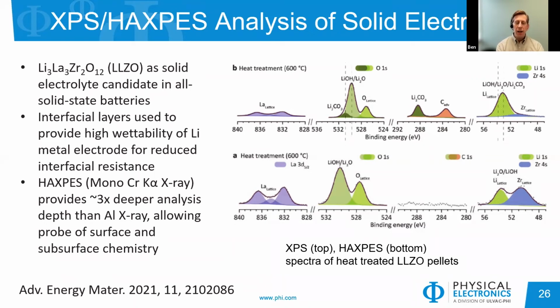In this case, there were LLZO pellets, and they are heat treating them and then applying an antimony surface coating to try to improve the performance of the material. But what we're looking at here is the uncoated materials, before or with a heat treatment. The top figure shows that we are seeing a lot of lithium hydroxide type species, and some lithium carbonates on the surface.